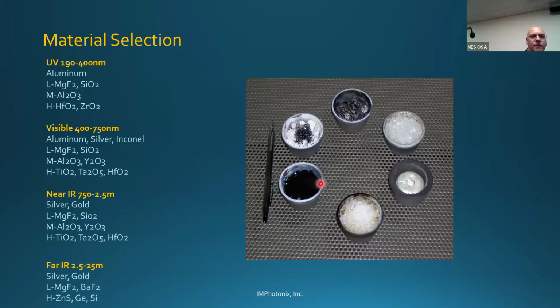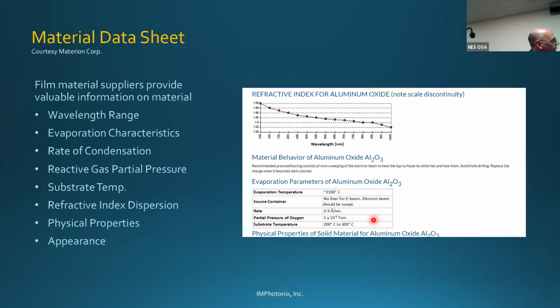This is titanium, which characteristically has a nice melt on it, pretty stable. This is hafnium dioxide and zirconium oxide. Those materials are more difficult to evaporate and form a film because they sublime. They go from the solid to the gas state with a very small liquid state. They tend to be very volatile. Silicon dioxide here, granular, silver, and last mag fluoride. These would go right into an electron beam gun.